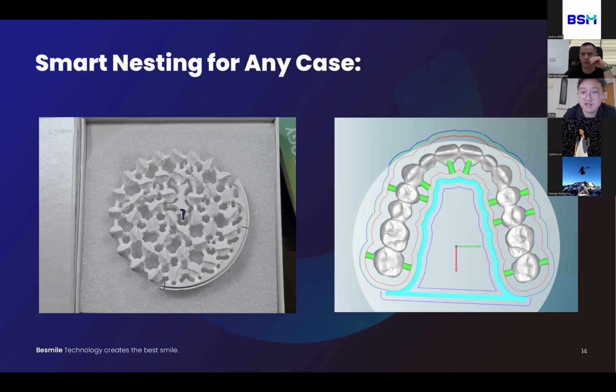You can see it's a hollow sintering frame. And the thickness of the stabilizer is 1.5 to 2 millimeters. So if the thickness of the bridge is bigger, we can increase the thickness of the stabilizer according to the thickness of the bridge.